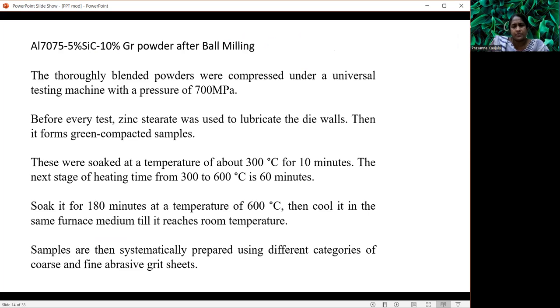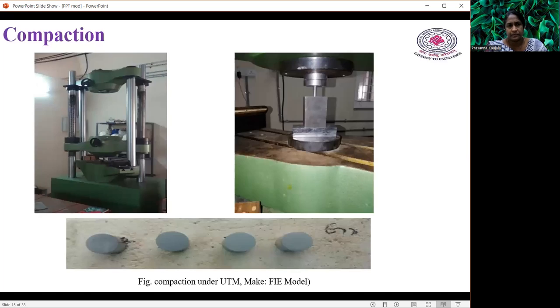Here, the blended powders were compressed under 700 megapascals. But before every test, zinc stearate is used to lubricate the die walls, and then it forms the green compacted samples. These were soaked at a temperature of about 300 degrees centigrade for 10 minutes, and again soaked for another 180 minutes at a temperature of 600 degrees centigrade, and then cooled. The samples are then systematically prepared using different categories of coarse and fine abrasive grit sizes. Then the sintering process is done.